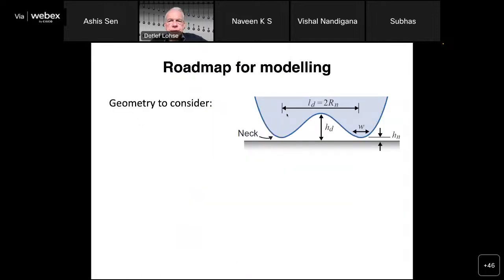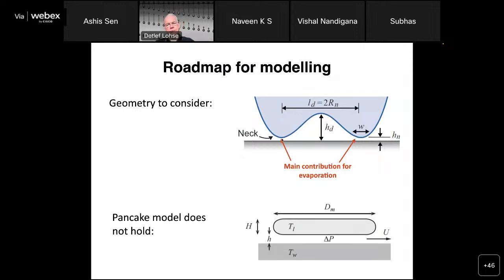But the interesting thing is in the middle. So here with this dimple, when you want to model the heat transfer from the substrate towards the droplet, you must, of course, know what's going on here. The main contribution for evaporation comes from here. And well, I must admit that in 2011, we were not so much aware of this.